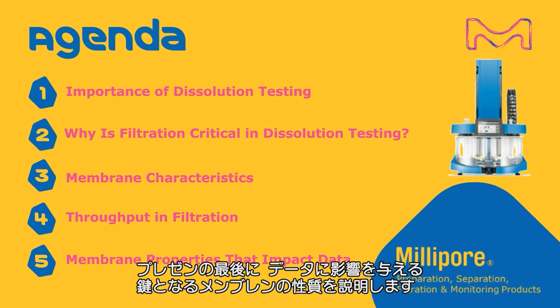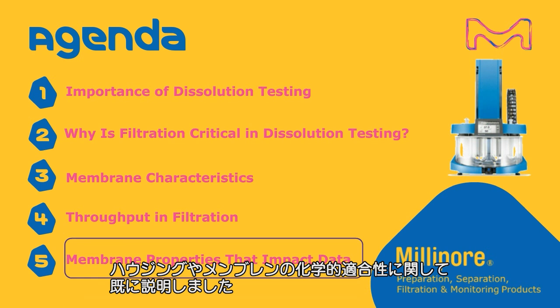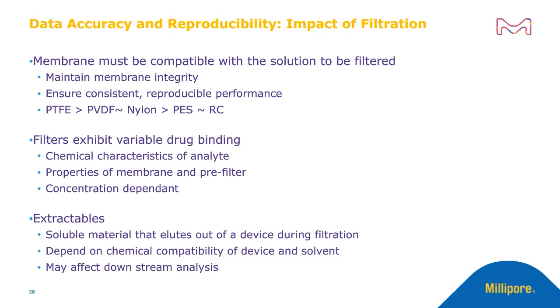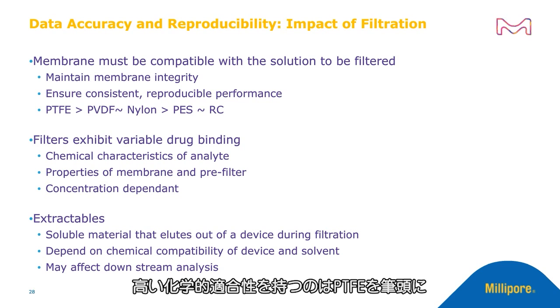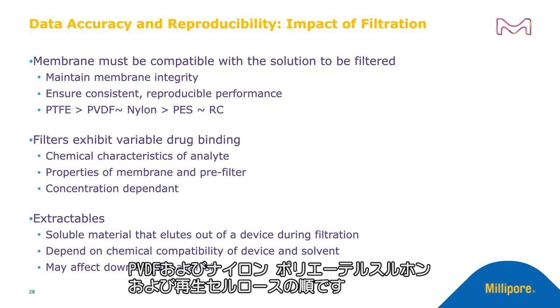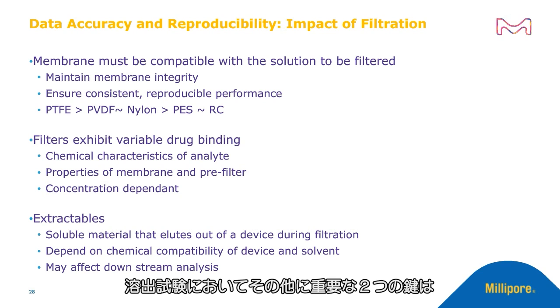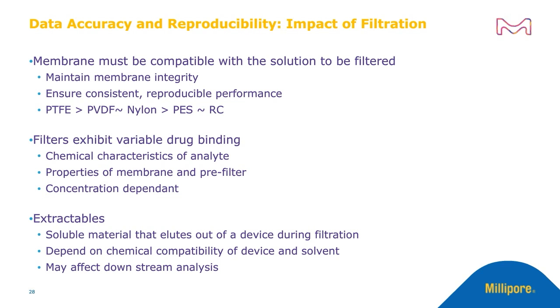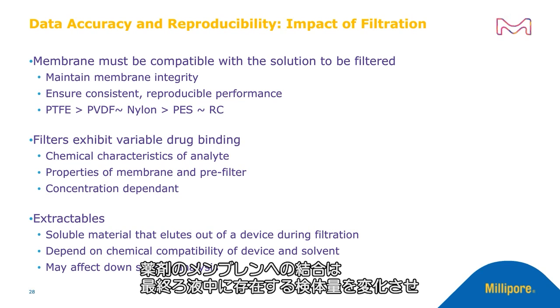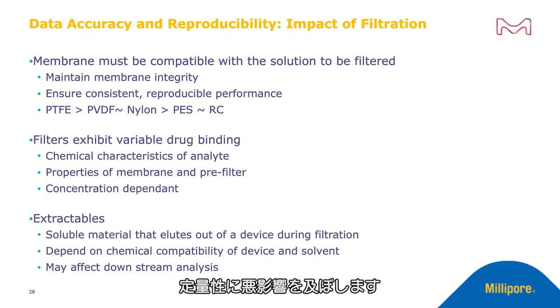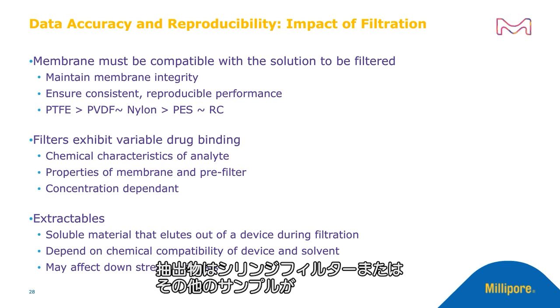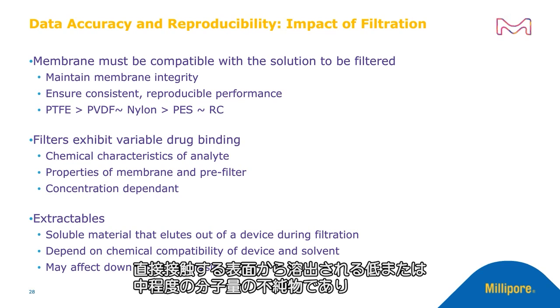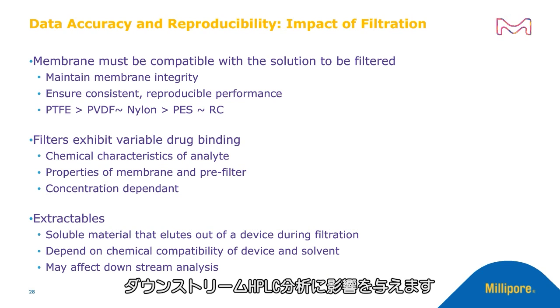In the final section of this presentation, I'm going to talk about some of the key membrane properties that impact the data. We already talked about chemical compatibility of housing and the membranes. And we saw that PTFE has the highest chemical compatibility, followed by PVDF and nylon, followed by polyether sulfone and regenerated cellulose. The two other key concerns of scientists working in dissolution testing are drug binding, as well as extractables. Drug binding changes the amount of analyte that is present in the final filtered solution, thereby leading to incorrect quantitation. Extractables are low or medium molecular weight impurities that get leached out from the syringe filter or any other surface that comes in contact with the sample, and those can impact the downstream HPLC analysis.